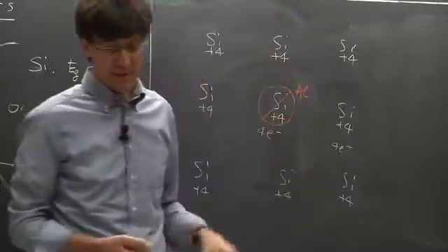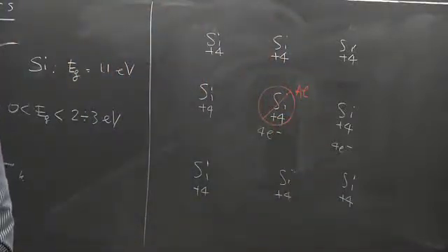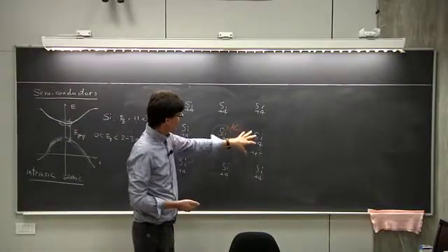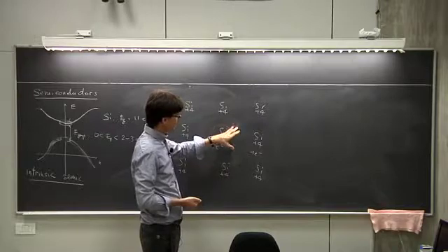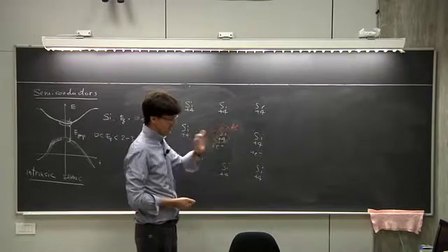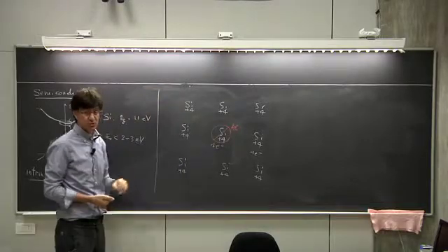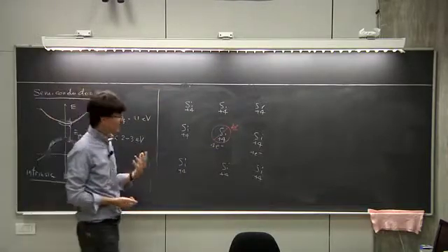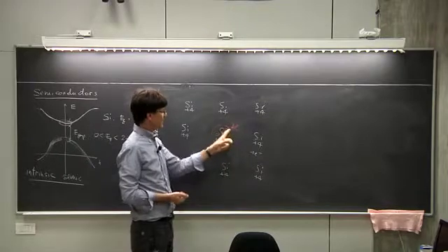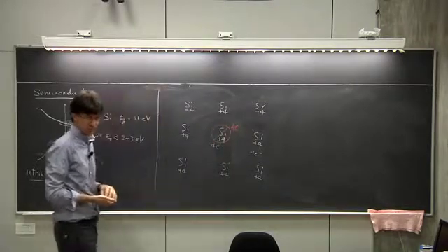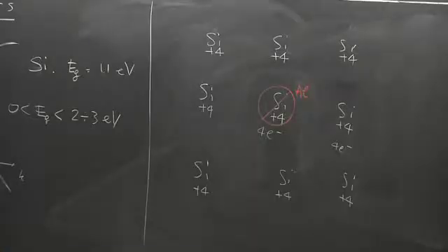So aluminum is close to silicon in the periodic table, and so it shares some of the chemical properties of silicon, at least locally. So the most stable location of aluminum, if you throw a little bit of aluminum in silicon, is to sit at substitutional sites. Substitutional means that it sits on sites where there is no silicon, and silicon is replaced by aluminum. Okay, as an atom.